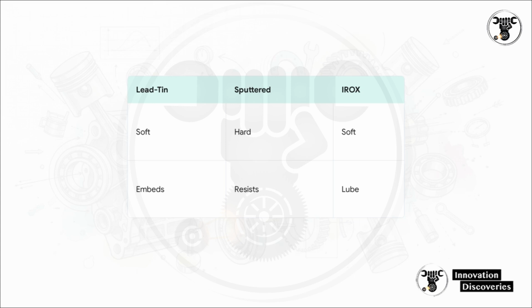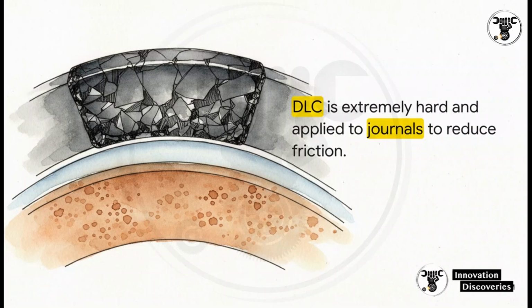And finally, the cutting-edge IROX polymer overlays. These actually embed solid lubricants, like molybdenum disulfide and graphite, right into a resin matrix. They are absolute lifesavers for surviving extreme boundary lubrication during harsh cold starts. But what about the absolute extreme end of motorsport? For that, we use DLC, or diamond-like carbon. Just look at that hardness, 1,500 to 3,000 HV. That is insanely hard. But remember our sacrificial bearing philosophy? Because of that rule, we actually apply this ultra-hard DLC exclusively to the crankshaft journal, never the bearing shell itself.